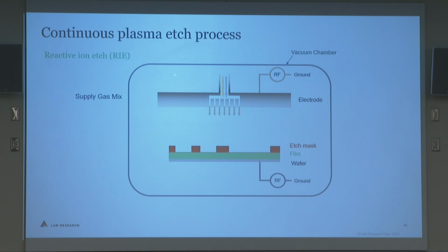So you supply your reactive gas mixtures again. It's a plasma process, so you're generating reactive species. And you've chosen the species so that the etch mask does not get etched, or it gets etched at a very low rate relative to the film, and you can remove the film. So a reverse example is if you want to remove silicon dioxide, you can add CF4, you create a silicon fluoride compound, which is a gas, it's volatile, so it goes away from the surface, and CO2, which is a gas, and you remove the film.